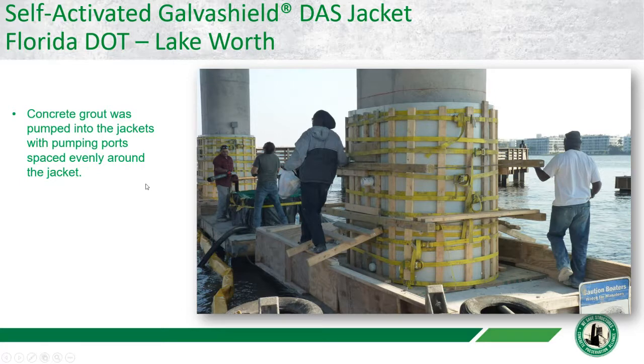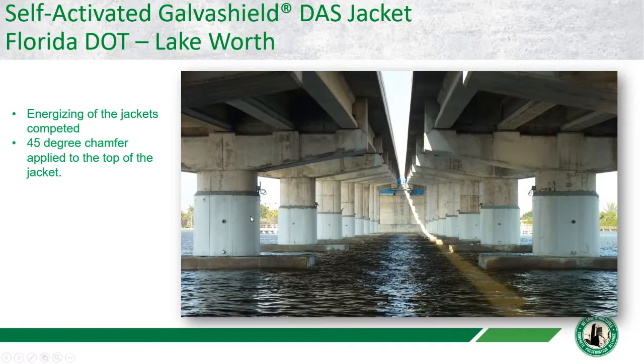So this is what the finished product looks like. You can see here all the jackets are installed. You can see the pumping ports and you can see the junction box on the top. This is where all the anode wires come up from the activated anodes and all of the cathodic wires from the reinforcements. There's typically a 45 degree chamfer that's also applied, and then the cathodic protection specialist will come in and actually energize, they call it energizing the jacket system, or connect the system up.